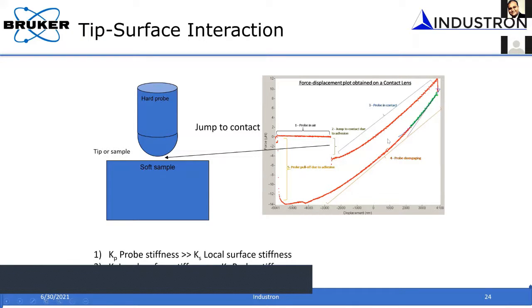Then you further load, and you pass through the adhesion to a repulsive regime. Then you start to see this typical load displacement curve. When you unload, you have adhesion between the tip and the sample, and then you have this pull-off. Pull-off gives you a measure of the adhesion between the sample and the tip. This is what you normally get on a soft sample, soft biomaterials. So you can't ignore all this interaction that is happening and simply assume it's a typical load displacement curve and make a measurement. You will be in error.